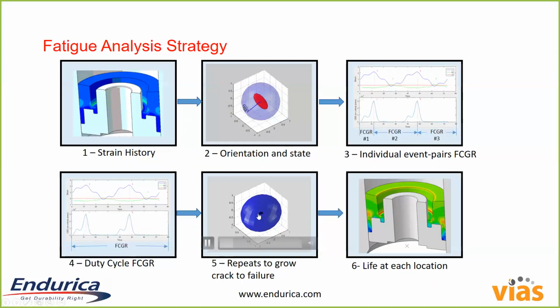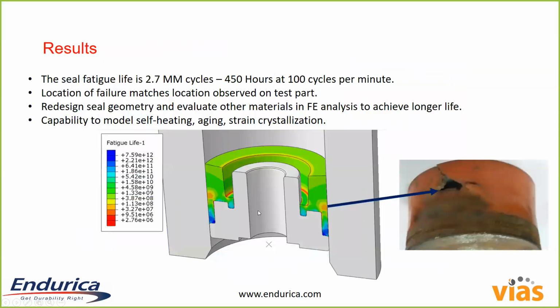For each plane, we play the load history into the crack, and the crack grows. And then, like I said, we repeat this process for every element, and then we plot fatigue life on the part. And so this is the final result. You can see we're predicting the shortest life is at this intermediate place on the seal. Here you can see the crack after it's initiated and torn through the seal, and you can see that we got the location right.